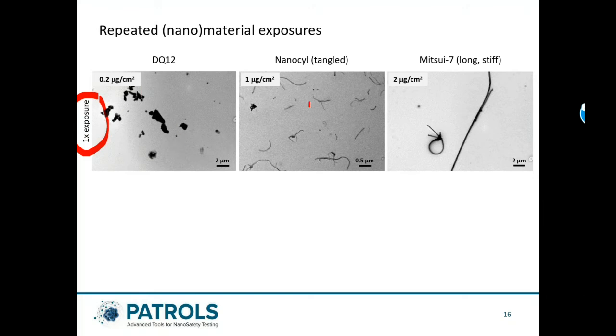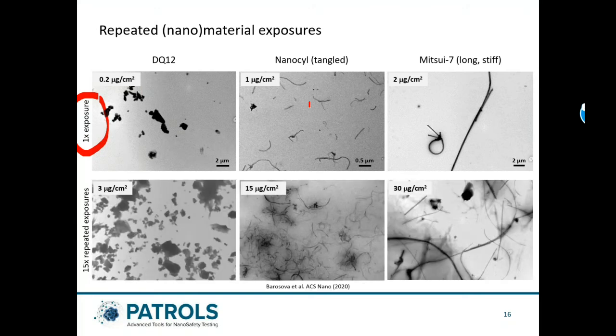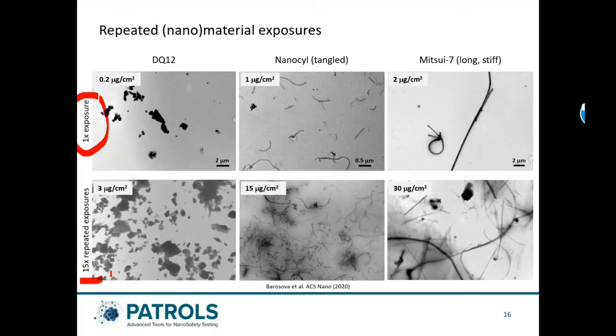So we did one exposure with the CLOUD system and could measure the deposition, and then we exposed our EpiAlveolar model every day over 3 weeks during the working days. This resulted in a total of 15 repeated exposures. You also see the range of deposition here, which was measured via the quartz microbalance.